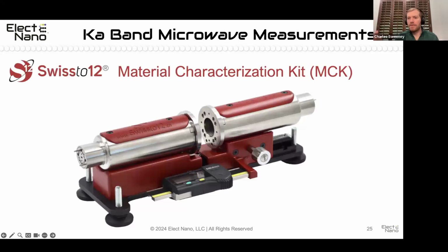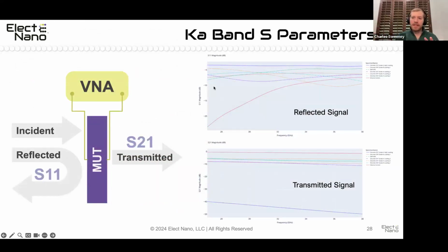And so our team did a lot of functionalizations and optimizing nanotube dispersions in silicones. We used a cool little fixture for measuring the microwave absorption in the Ka bands. It's a 2-port guided free space method for measuring those. I'm not going to go into too much depth, but effectively you use a vector network analyzer, you shoot a wave at it, you have an incident electromagnetic signal. Some of that gets reflected, that's your S11 parameter. Some of it gets transmitted, that's your S21 parameter. And by comparing those signal intensities, the S11 and S21 parameters, you can back out what your absorption, transmission, and reflection components to the signal are.